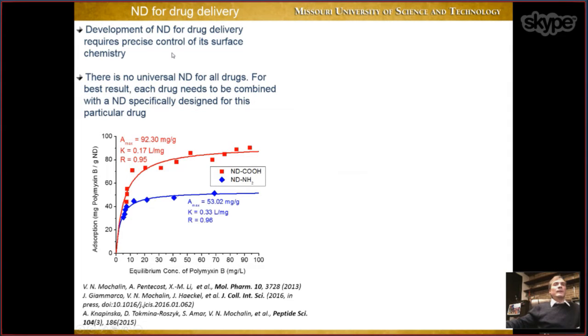For example, for drug delivery. And again, it was shown many times that it works for drug delivery. It works perfectly. Nanodiamond, by the way, is biocompatible. This material is around us for more than 50 years. And there are no papers indicating that this material would have any cytotoxicity or other harmful effects on cells. And that is what attracts attention of people working in drug delivery to this material. But again, you need to be very careful about surface chemistry. So my main message, which I'm trying to deliver with my work, is that you need to always pay attention to characterization, modification, and rational design of this material.